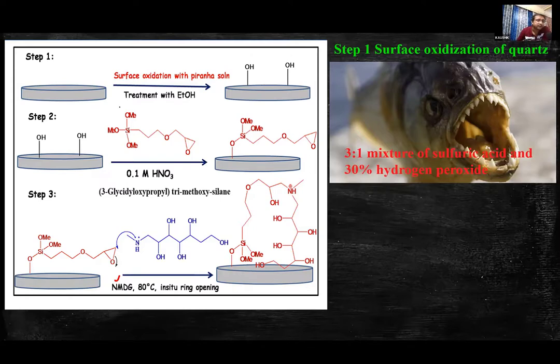We prepared this piranha solution and preheated it to 80 degrees centigrade. We dipped these quartz sample supports into the piranha solution for 30 minutes. After that, we took out the quartz sample support and rinsed it with Milli-Q water. Then finally, with the treatment with ethanol, these quartz sample supports are oxidized and SiOH groups are attached on them.